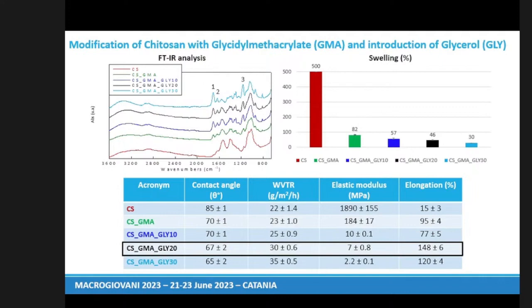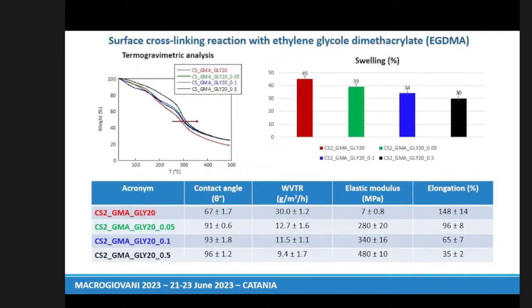For this reason, we decided to apply the cross-linking process only on this matrix. The cross-linking process was evaluated through the use of thermogravimetric analysis that shows an increase of thermal stability with the increase of concentration, and also a decrease in the swelling capacity of our dressing.